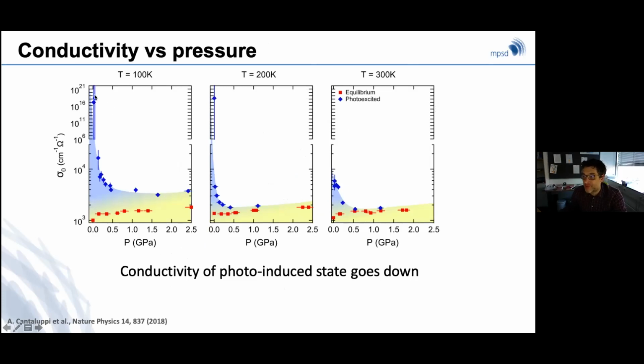And then as I apply pressure, what I find is that unlike in the equilibrium metallic state, for a certain interval of pressure, sigma 0 reduces. This is related to the gap closing, until you get to about 1 gigapascal, where sigma 0 starts growing again, indicative of a metallic response. So the photoexcited material at 2.5 gigapascal, although it is a state with higher conductivity, is also a state in which conductivity goes up with pressure.